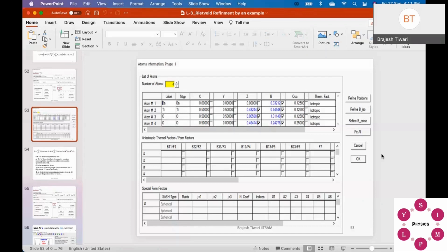So using the matching software, you try to match which structure matches with your structure. Take that structure, export CIF, and for your material you replace the atoms whatever you have. Suppose you are making strontium titanate, and you are able to get the match barium titanate. So instead of barium you replace with your element strontium, or whichever best matching you choose from the match software, and export that CIF.